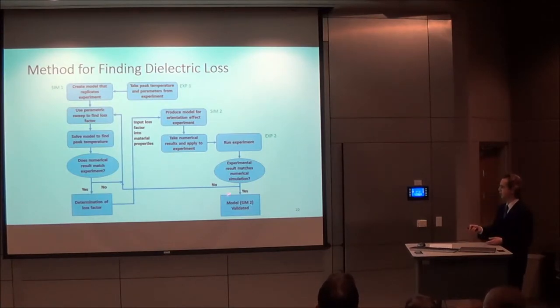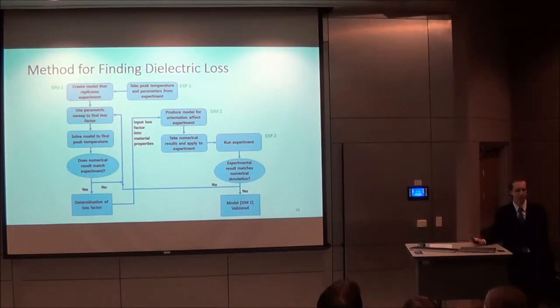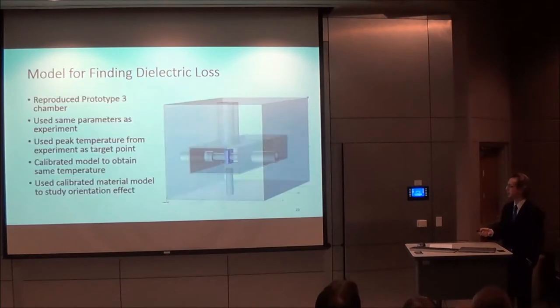Otherwise, that validates not only this numerical model that was made with the calibrated data, but also the model used to find the loss factor in that approach. And this approach was also used to determine the magnetic loss factor of ferrite, which will be important later in this work.